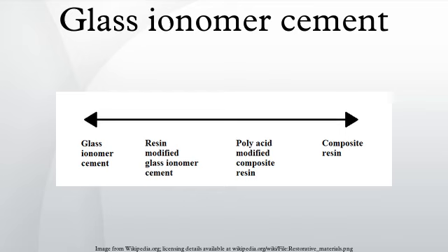Comparisons between resin-modified glass ionomer cements and conventional materials reveal that the shear bond strength of the former is generally greater, but that they show very low bond strength to unconditioned dentin compared to conventional materials. Conditioning therefore plays a greater role in achieving effective bonding with the resin-modified glass ionomer cements. In addition, when the enamel surface is etched with phosphoric acid, the bond strength of the resin-modified materials is close to that of composite resin bonded to etched enamel. This suggests, along with the effects of light curing, that the bonding mechanism of resin-modified glass ionomer cements may be different from that of conventional materials.